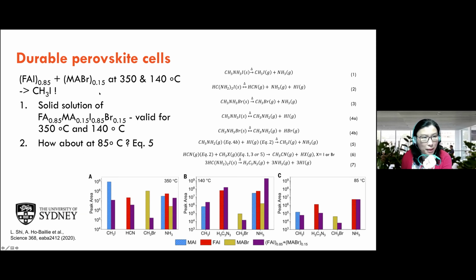Now, interestingly, when we mix the precursors, we found that we have CH3I. If you remember, CH3I is the signature product of MAI, but here we've got FAI and MABr. So there are two explanations. One is, if you mix the precursors, it becomes a solid solution, which is valid for high temperature. But how about 85 degrees? We think it's represented by equation 5, where the CH3I is produced by the methylamine from equation 4B, which came from MABr, reacting with HI, which came from equation 2, which came from FAI.